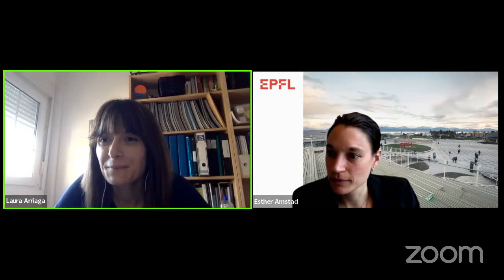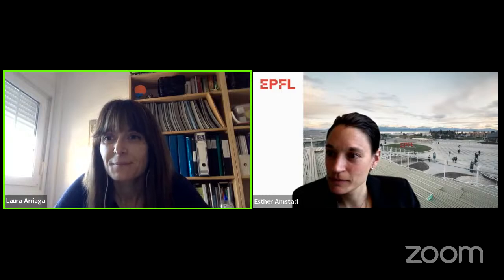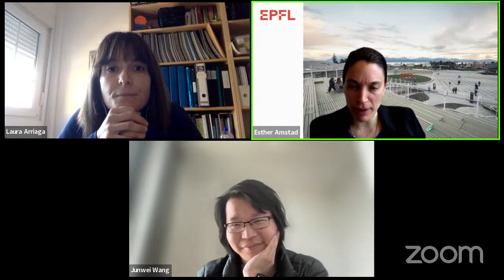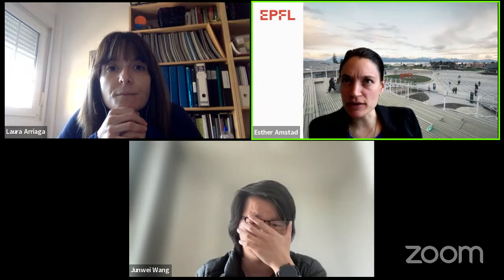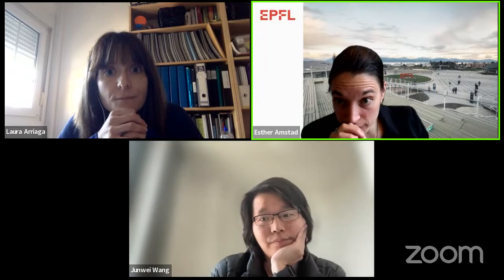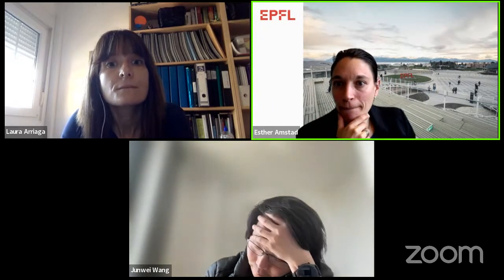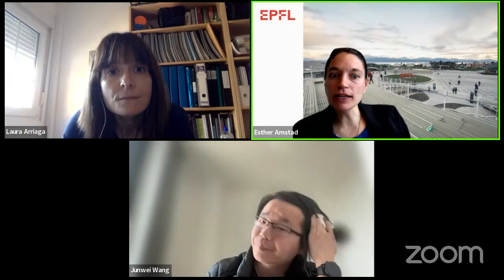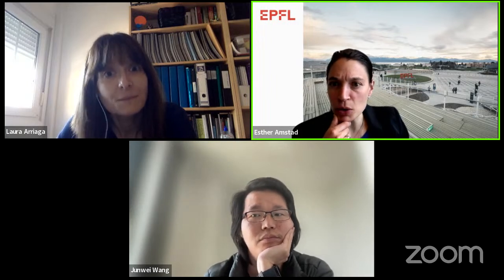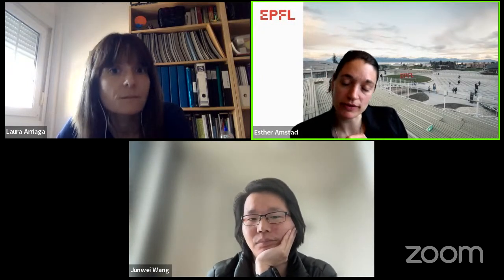Any other question? Esther, in which range can you vary the size of the droplets to make still the raw material? That is a very good question. As you know, for microfluidics, we can vary it conveniently between 50 and a couple of hundred micrometers. We recently introduced what we call a surface acoustic wave-based emulsifier. There we make airborne drops first, and then we immerse them into an oil by taking advantage of positive spreading coefficients. And there we can go to drop sizes between 1 and 10 micrometers. So there we gain an order of magnitude, more or less, which I think is important. Going lower than that, we still failed. If you really want to go lower, we use tip sonication, but then of course you're very broad in terms of size distribution.